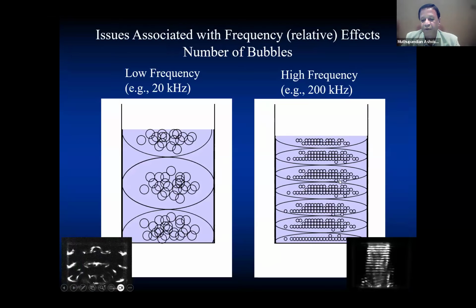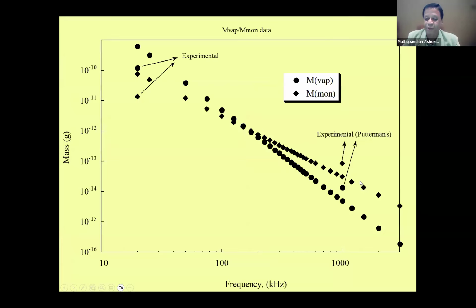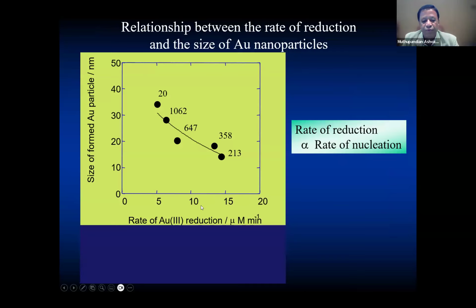But then when you go to very high frequencies, there is another factor coming into the picture. The bubbles are oscillating too fast, so there's no time for water to evaporate. If there are no water molecules in the bubble, then you will reduce the number of radicals. It's a very simple explanation. So simply what we are trying to show here is that the size of the particle is inversely proportional to the rate of reduction, okay?